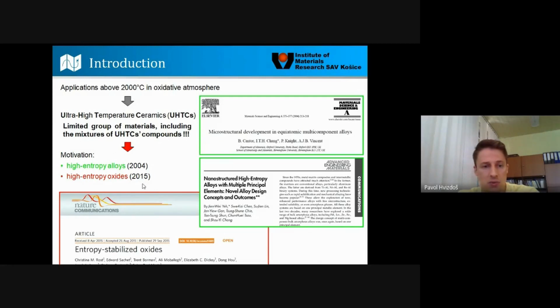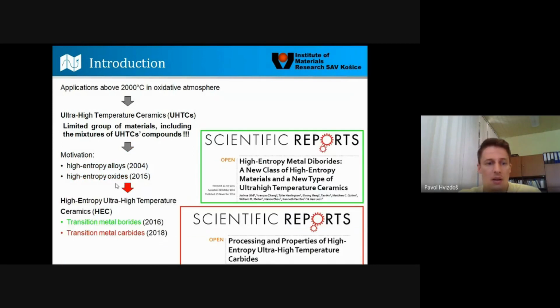So based on the success of processing ultra high temperature oxides in high entropy oxides, as let's say the counterpart of high entropy alloys, additional studies appeared on the ground. So transition metal borides were synthesized in 2016, and after 2 years, I mean, the English partners who we work with developed the transition metal carbides, and we had a chance to do some testing, characterization, and develop even more the materials. So this was in 2018.